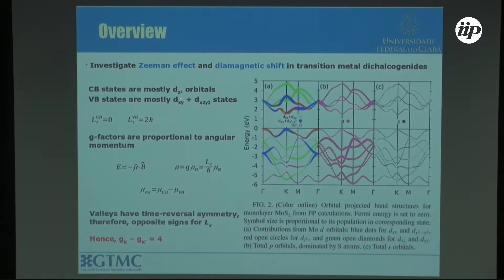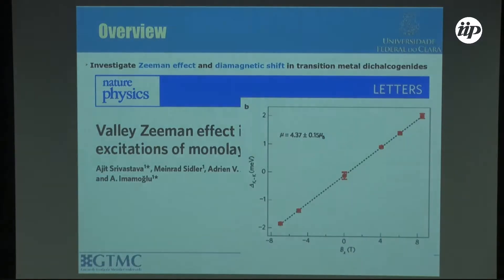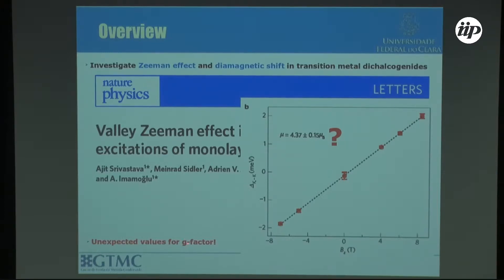That sounded like the end of the story, but the problem is when people started looking at different materials. For tungsten diselenide, they observed not 4 but 4.37, and this was really consistent — you can see from the error bars that this line is really 4.37. So where does this 4.37 come from? You get a G-factor that is not even an integer. Why is that? They started to see some unexpected values for this G-factor.